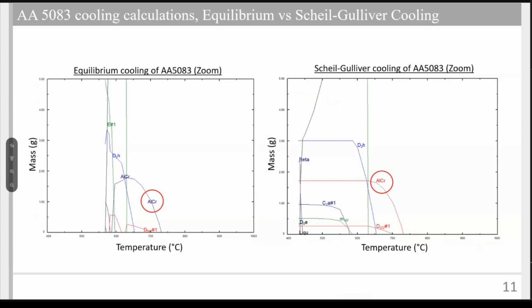For example, in both cases, the Al11Cr2 phase is the first to precipitate. Because in equilibrium cooling the phases can interact with each other, the phase is not present at the end of solidification. But in the case of non-equilibrium cooling, because the phases cannot interact with the liquid once they're formed, the composition stays until the very end of solidification.